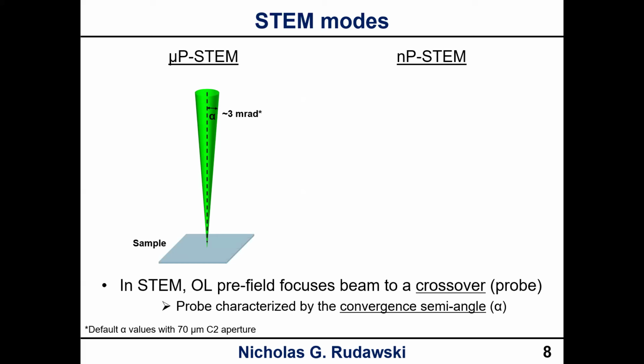So the default value with the 70 micron C2 aperture on our Themis Z microscope is 3 millirad. Now in the software, it says 1.5, but that's not accurate. I've measured it. It's about 3. So the alpha value in microprobe indicated in the software is not accurate. That's important to note. It is accurate in nanoprobe mode if you do the condenser calibration properly, but it's not accurate in microprobe mode. Anyways, a little bit of a side jaunt there.